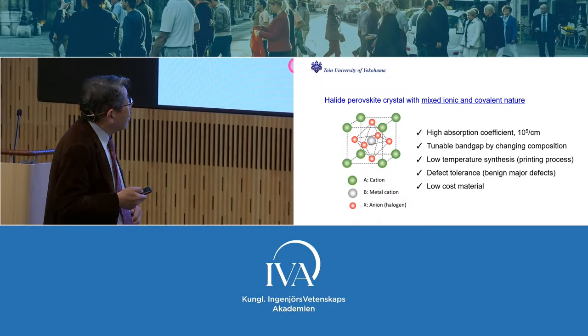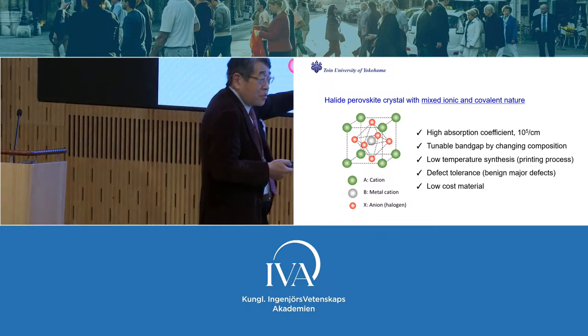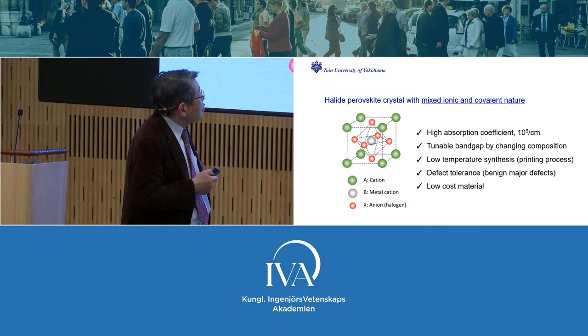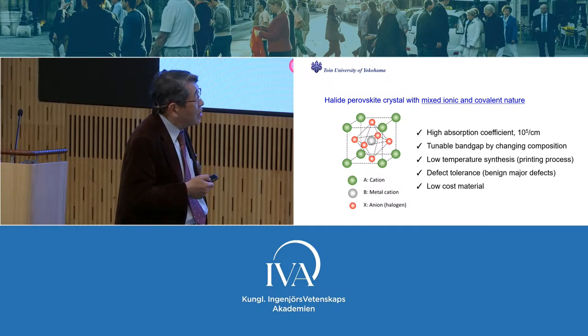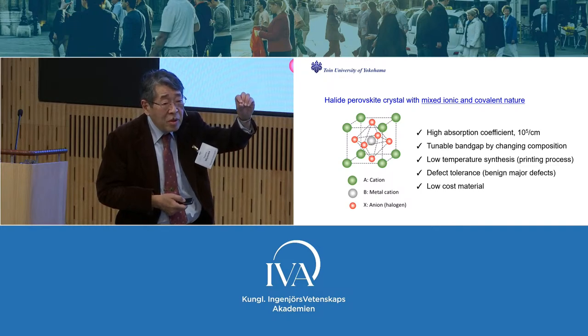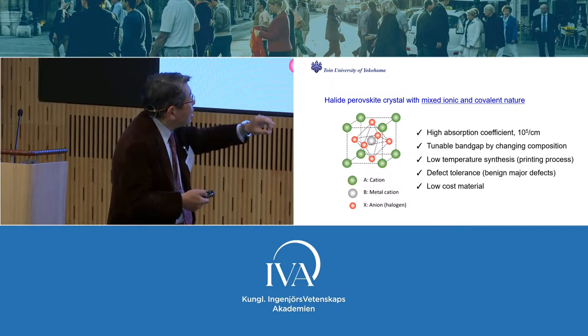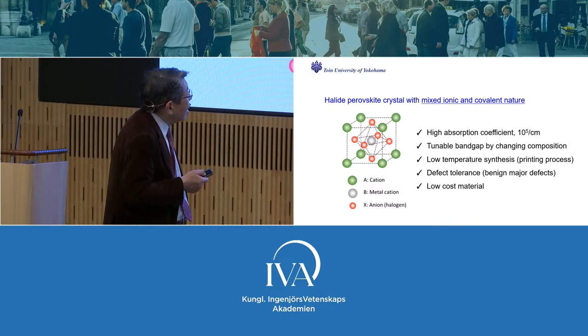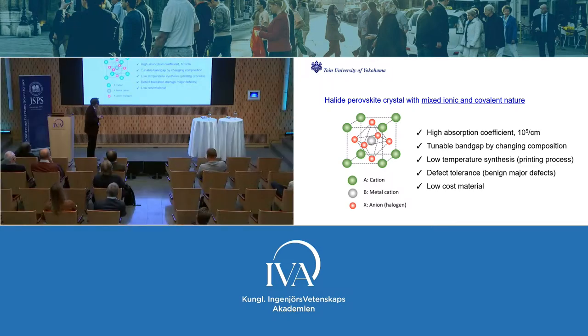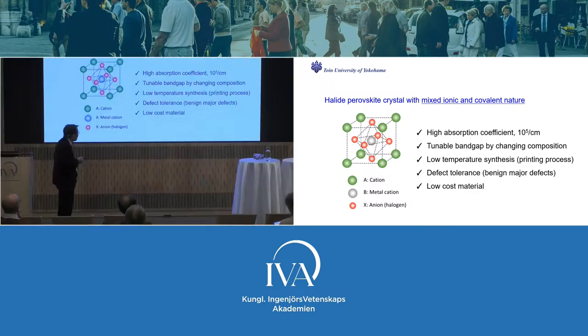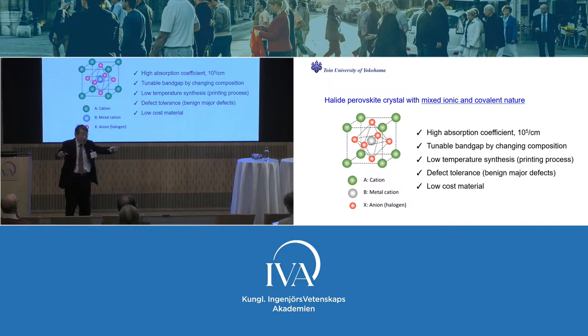So what is very special about the perovskite crystals? This is a mixed ionic and covalent nature. This is ionic crystalline because of having the halide here. And the absorption coefficient is very, very high, 10 to the 5. So only a 1 micron thick film can totally absorb the incident light. And the band gap is tunable by changing the composition of halide, and we can synthesize the material at low temperature, and there was fortunately the so-called defect tolerance nature. It's the benign nature of defects. And the material cost is very, very cheap. Roughly, 1 square meter of large perovskite film costs just $2.